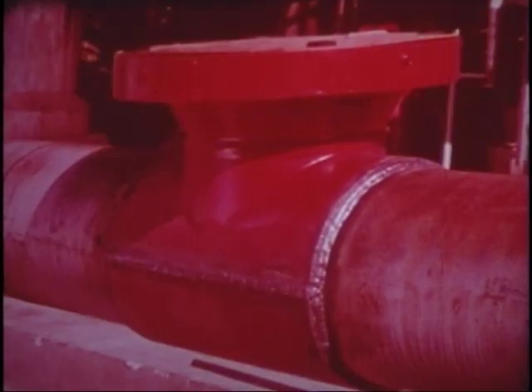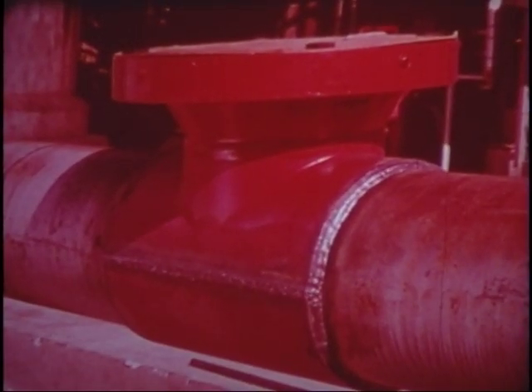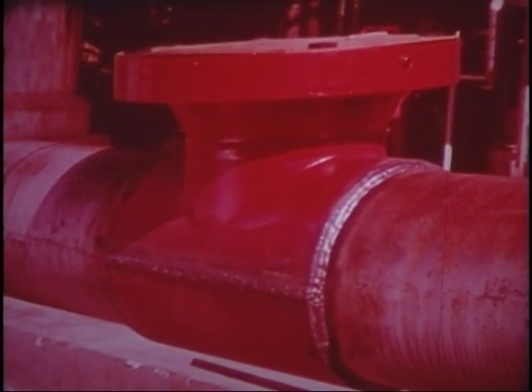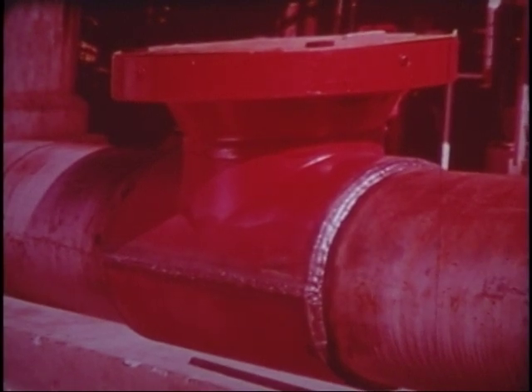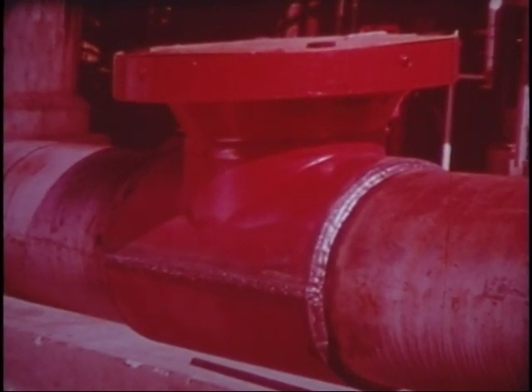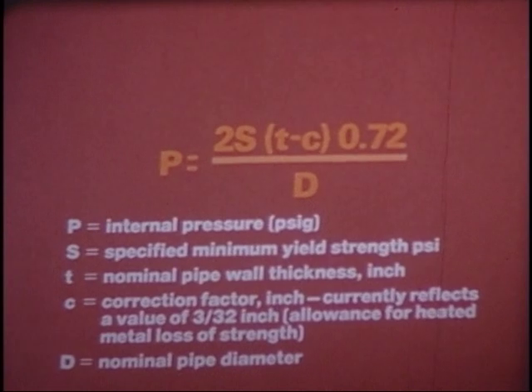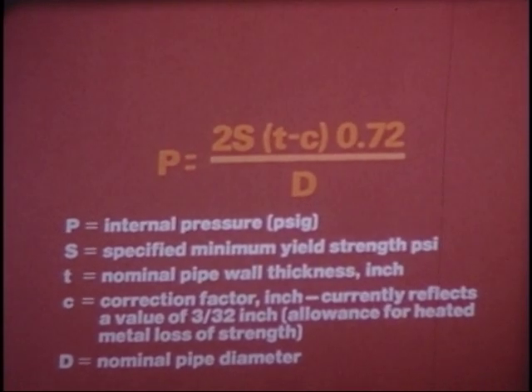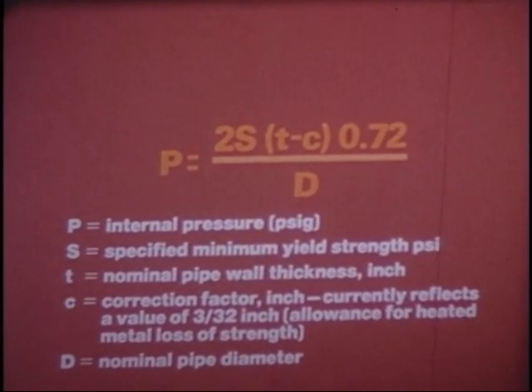The minimum allowable pipe wall thickness should be 0.156 inch or greater. The electrode should be manipulated to maintain a heat balance between the fitting and the pipe. The weld attaching the fitting to the pipe should be made circumferentially, not perpendicular to the hoop stress of the pipeline. Reduce pressure in accordance with ASME Gas Piping Standards Committee's recommended formula.